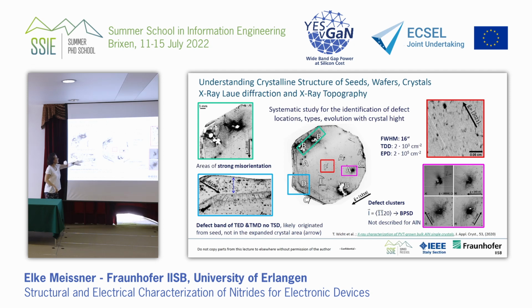So you see here, this is where the arrow is, that we have expanded the crystal by that. And this is, of course, what the ones who make the application with the devices want, something like 100 millimeters, so 4-inch diameter, or 6-inch diameter, or 8-inch diameter. Then they say, okay, if you want the aluminum nitride to be the next material, then grow a crystal which is even larger. And you see that you have to deal with these defects, because any of those contrasts is a defect. So you see this crystal, which is on the order of maybe 30 millimeters in size, and you see, okay, there are defects here, many, there are defects here. They should all be not there if you want to make a device. If a device would be on such a place, then it's trash.